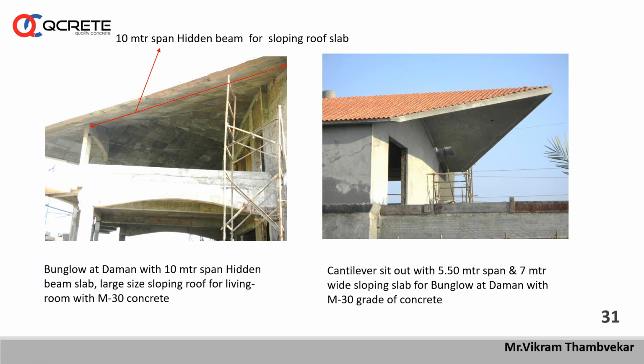To avoid this beam, I provided a 10 meter span hidden beam with the sloping slab on this sitting area. The thickness of the entire slab is only 150 mm, and we have provided a hidden beam for the span of 10 meters. I am emphasizing that this hidden beam slab effect is possible only by using good quality concrete, because if you provide more and more steel and the concrete quality is not good, nothing will happen. There will definitely be deflection or failure after a certain period.